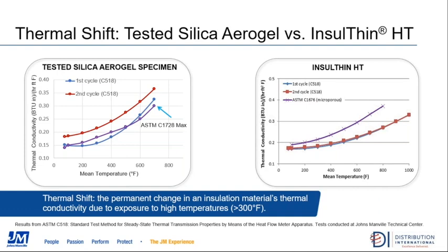So we found with aerogel, it doesn't happen with any other product we've ever tested, that after you cycle it up to the high temperature and down, and we're looking at the graph here on the left, and then up again, the thermal conductivity changed. It doesn't happen with any other product, whether it's calcium, perlite, mineral wool, Insulthin, foam glass, anything else we ever tested. But the thermal conductivity changes by up to 20%.